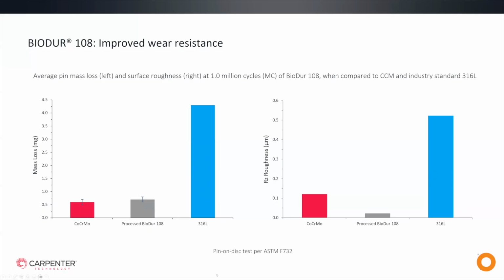So as you'll see, if you have an opportunity to walk through the white paper, in the white paper we talk about how we down select it to an appropriate level of cold work, and also further details are in the patent. And with that down selection, we can get a comparable wear resistance of a strain hardened BioDur 108 to both the cobalt chrome and well exceeding the 316L.